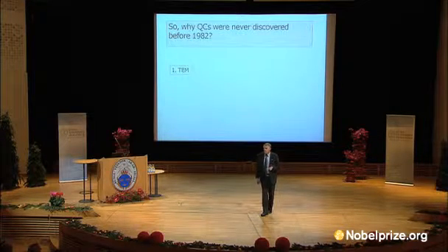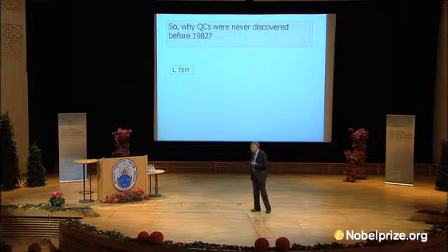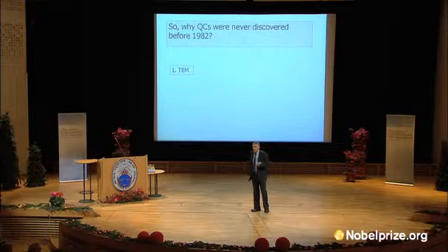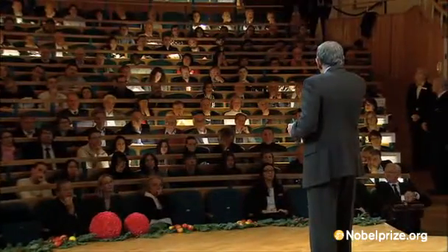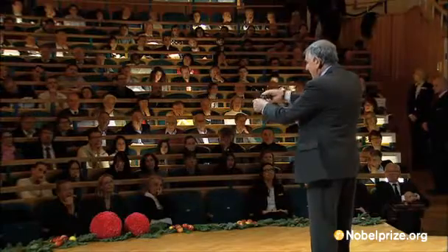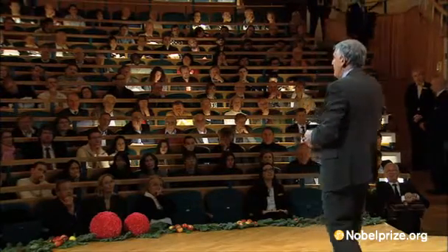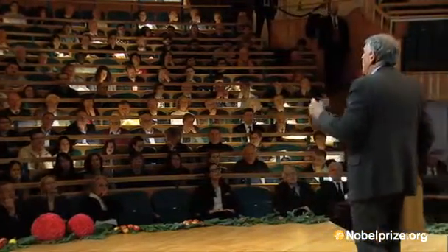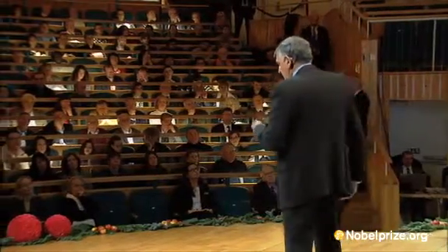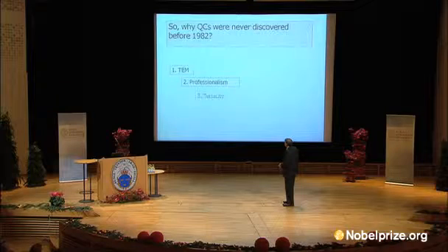You could not get a single crystal diffraction pattern by X-rays from crystals the size of which is 2 microns. You have to have something that you can hold in your hand, something that you can feel between your fingers, in order to put it on something and take an X-ray diffraction pattern. And these were available only 3 years later. So TEM must have been the tool of discovery.